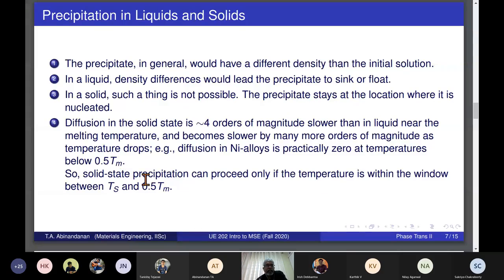So if you quench this nickel alloy from 1400 or whatever to room temperature and hold it there, you would not see any precipitation whatsoever. Precipitation requires aluminum atoms to come together to form these Ni3Al precipitates. And that requires diffusion. Since diffusion is practically zero, the entire thing can be completely suppressed. It will remain as a solid solution at room temperature for years and years to come.